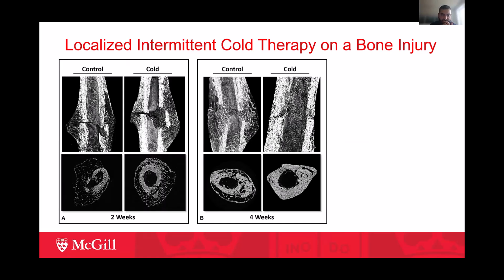So just to recap on what Dr. Merle went over, our preceding studies showed that there was a facilitation of the fracture repair process following daily cold therapy, in which there was enhanced mineralization, especially within the fracture callus region, 14 days after treatment, and earlier signs of bone remodeling up to 28 days after treatment within a mouse model. This led us to consider possible mechanisms that may explain the increase in mineralization and to further dig into how that might come to be.